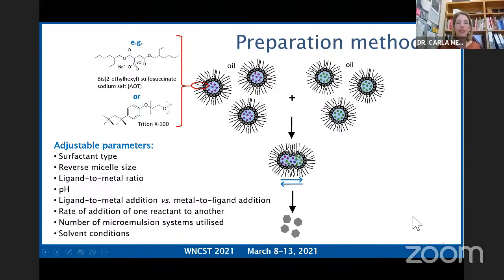So while this is fantastically exciting because we have a very high level of control of all of these different parameters, again, in a way that we don't necessarily have using more conventional approaches for MOF formation, you can see how very rapidly this would require a very high number of experiments in order to test all of these different parameters, some of which can easily be isolated, and others, some of these parameters are inherently linked. So it does become quite complicated very quickly.